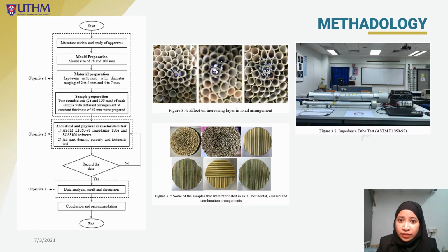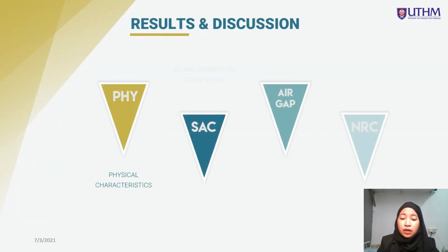Next, the acoustical properties were measured using the impedance tube method based on the international standard ASTM E1050-98 as shown. Then a gap of 0 to 25 mm in 5 mm increments is introduced in each sample. The NRC is calculated using the equation, by taking the average value of the sound absorption at 4 different frequencies. Moving on, there are 4 different topics that we are going to discuss in the results and discussion, which are the physical characteristics, sound absorption coefficient, influence of air gap, and also noise reduction coefficient.